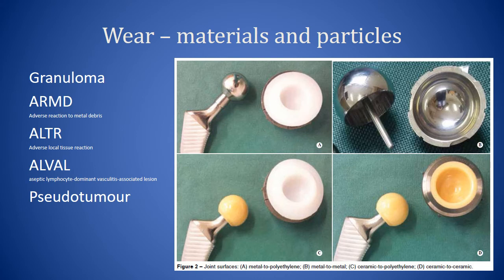The body responds to these particles in various ways. Commonly, a granuloma will form with polyethylene particles, and this is the vast majority of revisions that we are seeing from the old style polyethylene done more than 10 or 15 years ago.